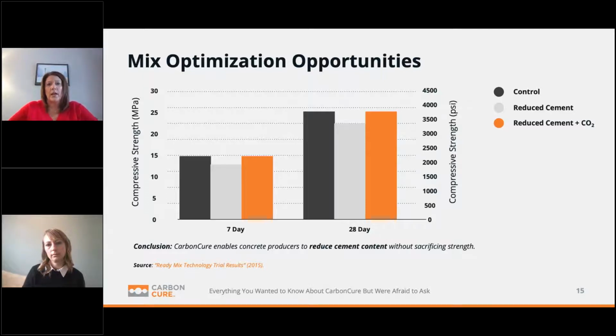So what you see here in this slide, higher strength gives us the ability to adjust concrete mixes and reduce the cement content. And that's where the real value of the technology comes in, especially in relation to carbon savings and what we can do, which Christy will talk about in a bit. But what we're looking at in this example is a case study that we did, a normal concrete mix that would reach 4,000 PSI at 28 days. That's the black bar, the control mix.